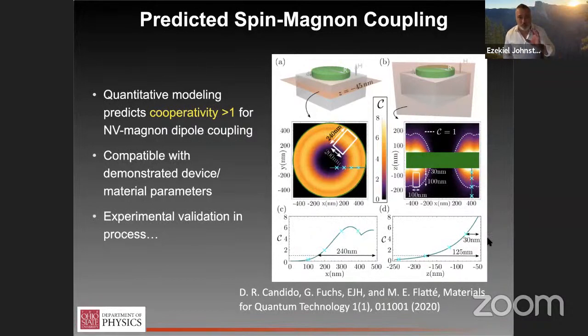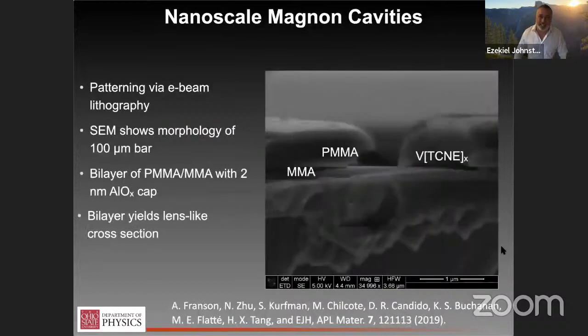And then the question is, well, okay, historically, we know thin films of V[TCNE]x have appropriate parameters. What happens when we actually try to build these resonators at micron length scales, and can we pattern, et cetera? Of course, that's a bit of a straw man. I wouldn't ask that question in a talk unless the answer was yes. And so I'll just quickly say we use a modified e-beam lithography technique to essentially do an in situ shadow mask. We do CVD through a window in the PMMA-MMA bilayer.